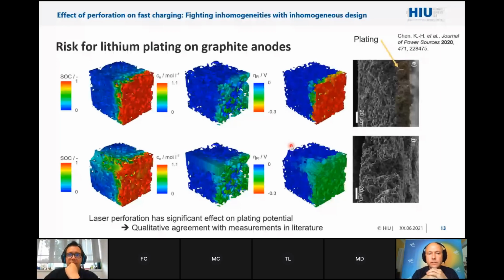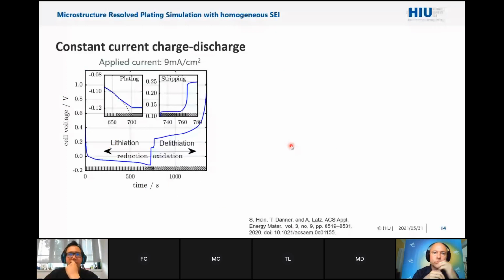Now let's look a little bit closer at what is happening during the actual plating event. So far we just tested where plating is going to happen. Now we are really simulating plating. So we are not only saying it's going to happen at the separator, but we simulate how much lithium is deposited and how much lithium is stripped if we change the current.